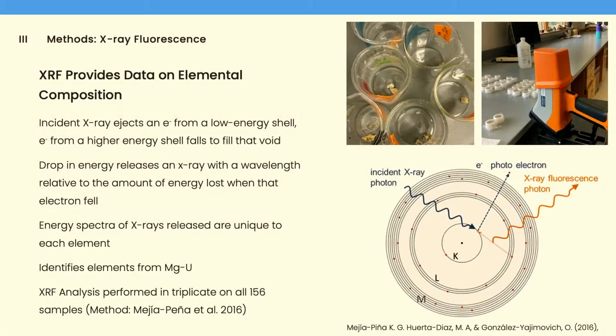The next major technique that I used was X-ray fluorescence, which provides elemental composition data. X-ray fluorescence works by using an X-ray to knock off an electron from a low energy orbital, one of those inner orbitals. That's the incident X-ray in that bottom figure and diagram. When it knocks off that inner electron from a low energy orbital, an electron from a higher energy orbital falls to fill that void. When that occurs, it releases energy in the form of an X-ray. The wavelength of that X-ray is determined by the amount of energy that's released when that fall occurs. And so the spectrum of X-rays released are unique to each element and is what allows us to determine the elemental composition of the sediments.